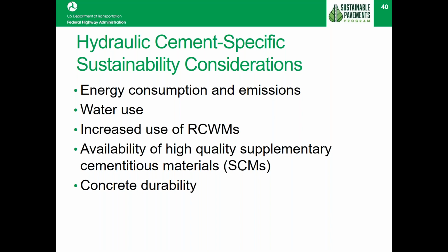Mainly because cement production is such a high energy intensive process, and it also produces a lot of greenhouse gases. The main thing to do with concrete is reducing the cement content. So Portland cement production is such an energy intensive process. 74% of energy used and 81% of greenhouse gas associated with cement and concrete industry is associated with cement production itself. So the key to reducing the carbon footprint is reducing the use of cement.